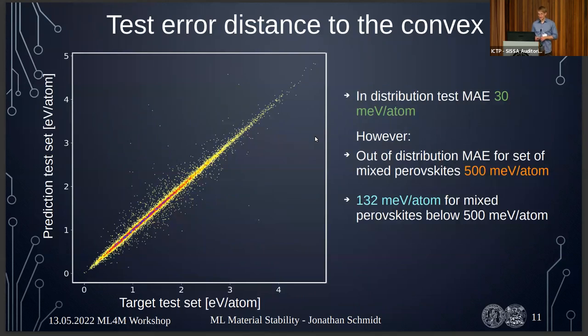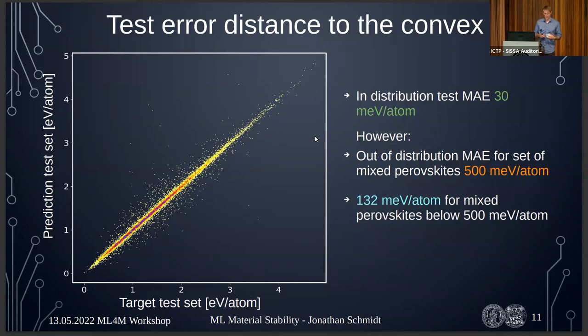We trained on this dataset. One pitfall already mentioned in the first talk: we can get better-than-chemical-accuracy MAE on a random test set, but that's just the in-distribution error. When we remove all mixed perovskites — removing all materials with the same composition and space group — we end up with an error of 500 meV per atom. There's also a distributional shift of about 1 eV because those held-out materials tend to be rather unstable.